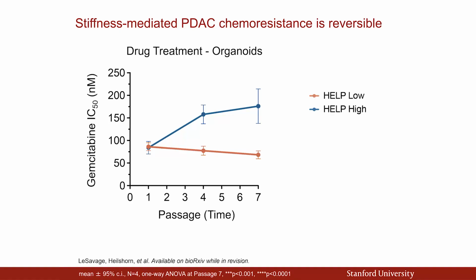And then my student did a really clever experiment. So this is just another way of quantifying that data that you already saw through the micrographs. The IC50 is the concentration at which 50% of the cells would die in response to the drug treatment. And so you can see in our high stiffness gels, as the passage of time goes on, the cells become more resistant. You have to give more drug to kill 50% of them. But if you take those cells and switch them into a low stiffness environment, they regain their sensitivity to the drug.